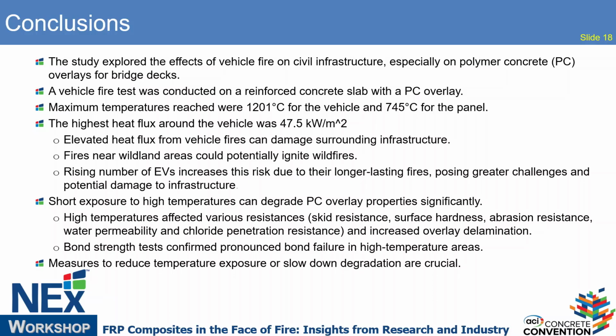Even though we did the delamination test with the IR camera, we didn't take samples there to see whether the delamination actually happens. But we did the bond strength test, which in some way confirmed the significant bond failure in the high temperature areas.